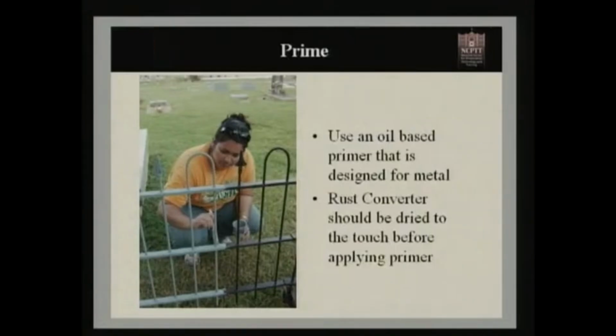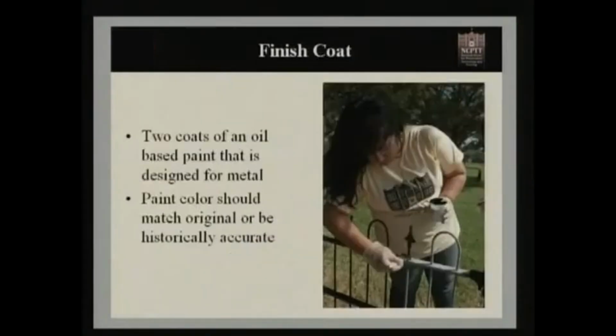In choosing a primer, you want to choose an oil-based primer that is designed specifically for metal, and especially for exterior metals. One or two coats, it's a personal preference at that point. Once your primer is completely dried, then you want to move on to your final surface treatment. You want to use one to two coats of an oil-based paint that is specifically designed for metals. If we move on to the next slide, there again, oil-based that's designed for metal and exterior metals at that. Paint colors should match the original or at least be historically accurate.